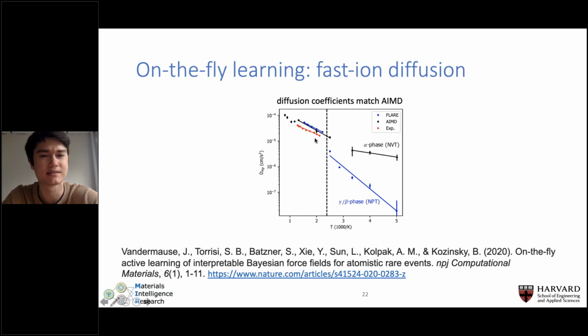So this system has been studied for several decades, and there's quite a bit of experimental data out there to compare to. And you can see we're getting the activation energy of diffusion pretty much correct. So there's good overlap with AIMD, which is sort of our ground truth. How are we comparing to density functional theory? For this material, DFT doesn't do a terrible job. There's reasonable agreement with experiment. So that's an encouraging sign that we can start to sort of apply this to more complex materials.